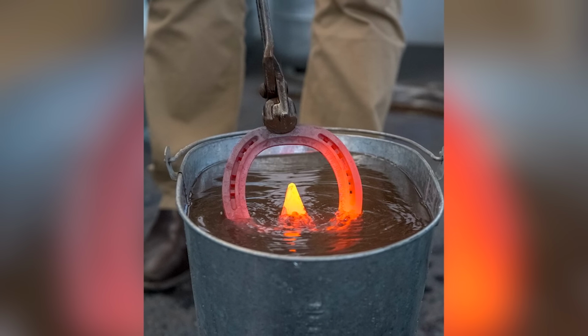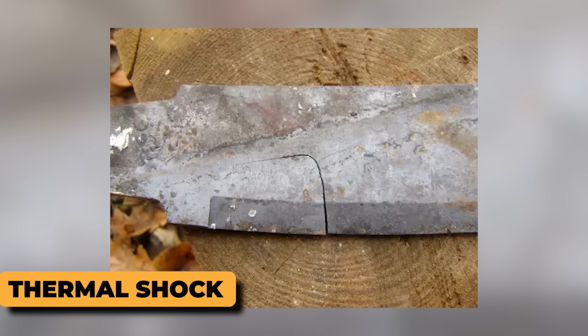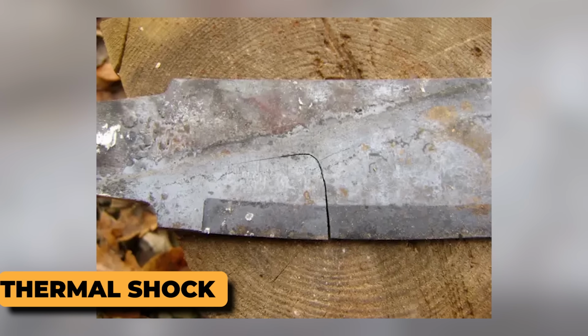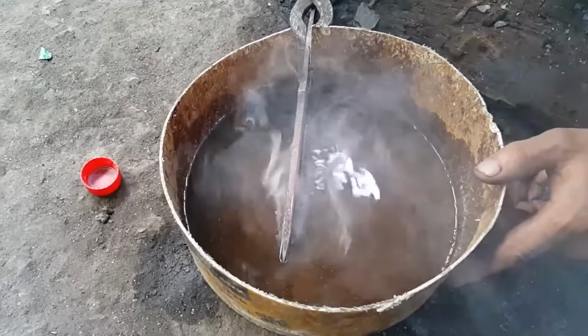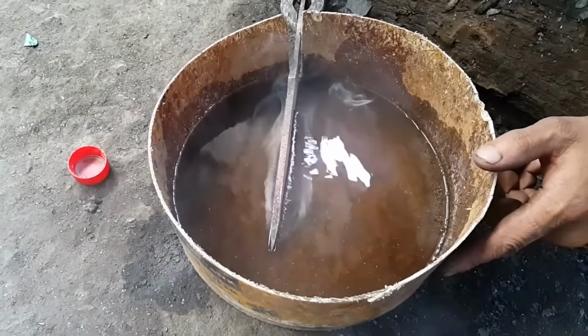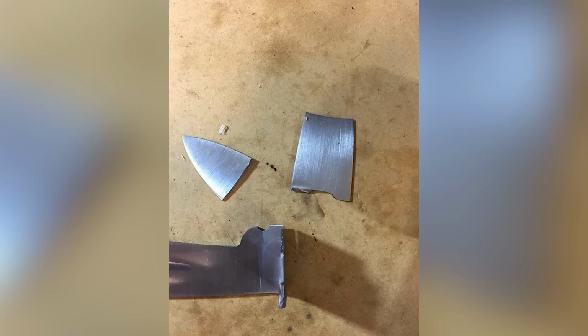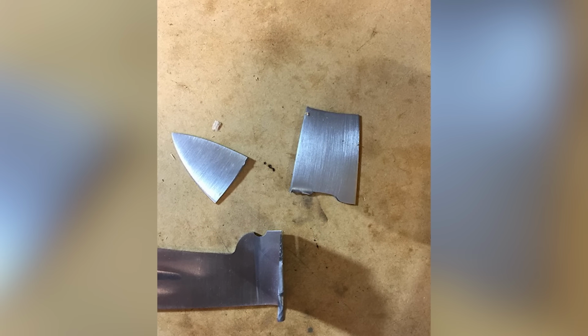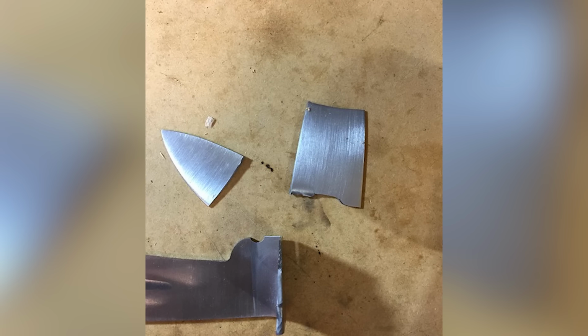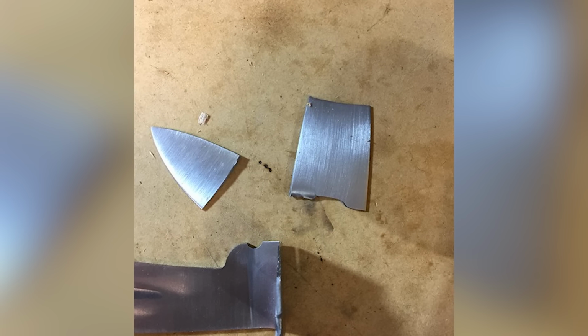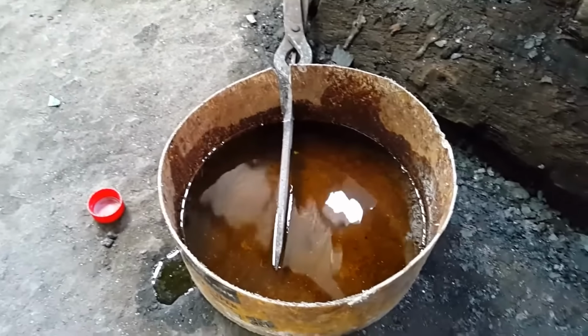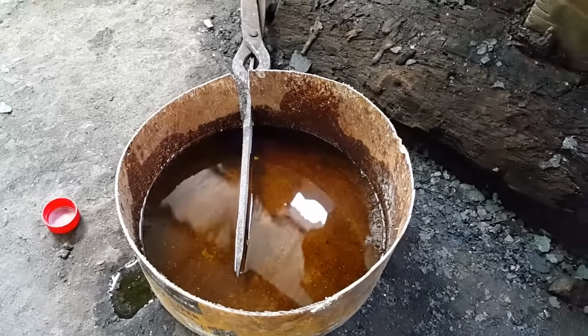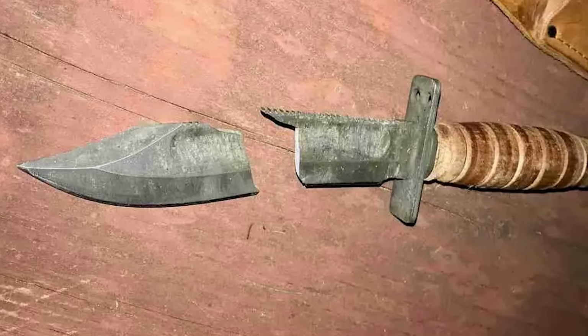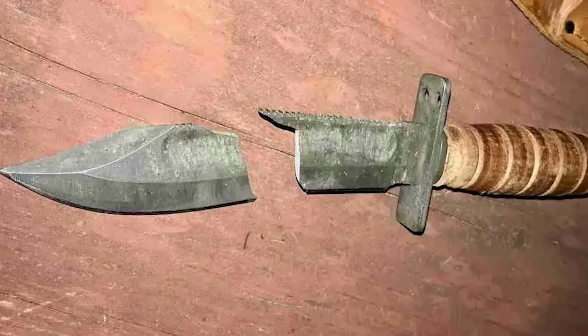But quenching also brought a risk: thermal shock. The blade could snap in half with a gunshot crack. Some smiths held their breath because after 30 hours of work, the whole thing could die in seconds. There's a story in old sagas of a smith who lost 3 blades in one day and finally threw his hammer across the forge, swearing never to touch iron again. If you heard a ping echo through the workshop, you knew the blade had split. That sound haunted blacksmiths worse than any war drum.